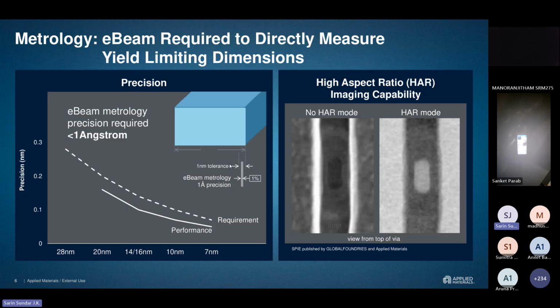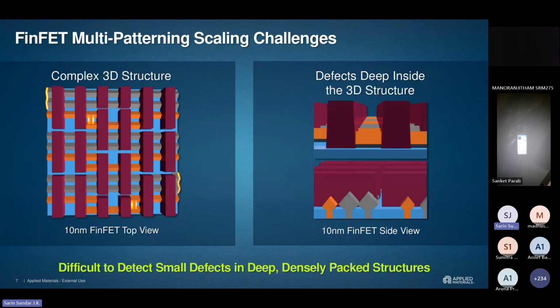So on the left-hand side, if you see, if it is a 1 nanometer tolerance of the layer of your deposition or etch layer, the metrology precision should be about 1 angstrom. So less than 1% should be your precision. So tolerance and precision, these are entirely different, right? So even when you measure a defect, you have to classify that actually it is a defect.